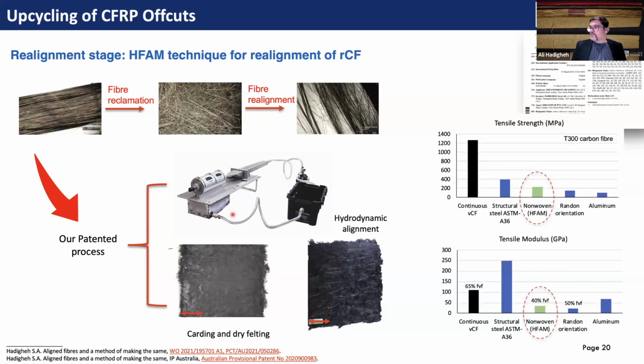And if we look at the non-woven format of our technique comparing to continuous virgin fiber, obviously that's far lower, but we expected that. We never can achieve the continuous virgin fiber, but that is something between aluminium and structural steel. So that is quite reasonable. And if you consider this is T300 carbon fiber, and if we have T700, you can see that the mechanical properties are getting very close to steel. So it is quite competitive.